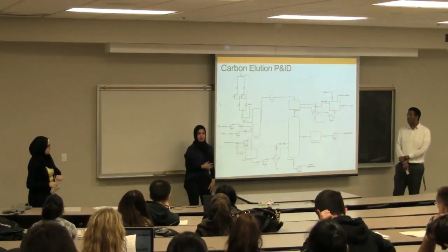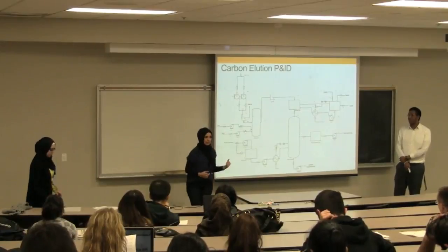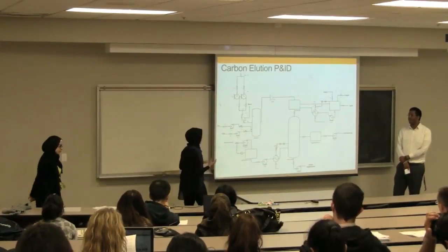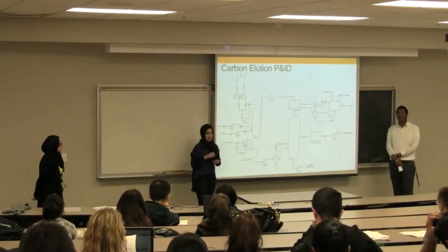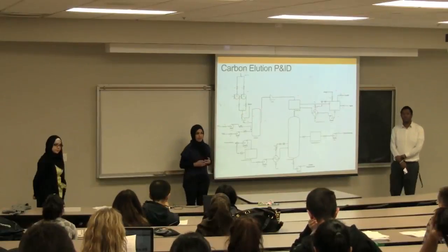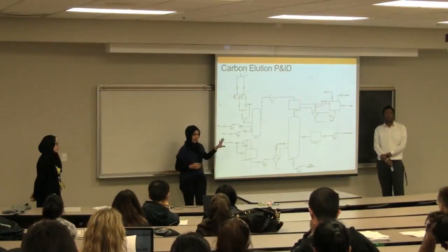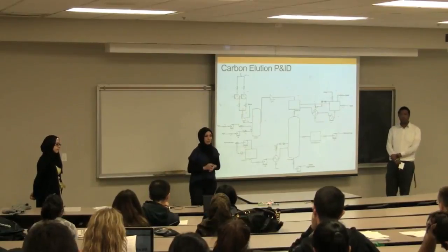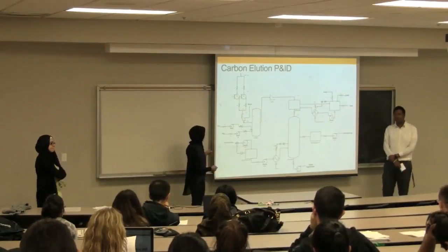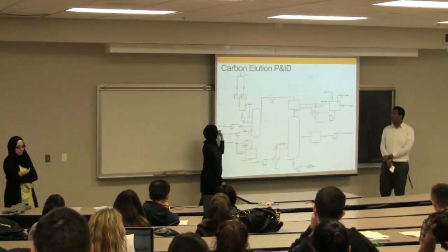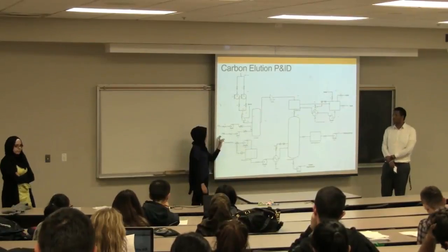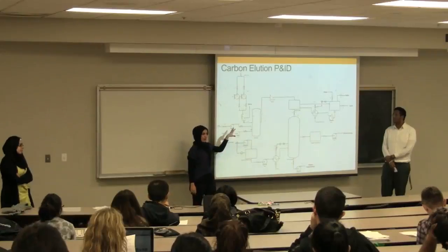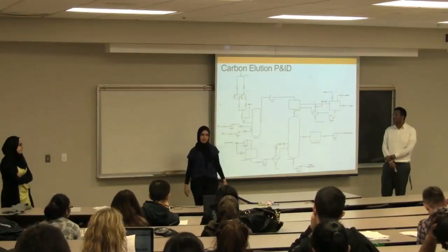which is actually a very important step because what we're doing here is we're trying to treat carbon fouling. Carbon fouling is essentially the buildup of soluble and insoluble materials on the carbon active site. It's important that we dissolve these foulants because we don't want the gold to be competing for these active sites with other materials. So in order to do that, we have to pump hydrochloric acid and water and essentially go through a washing cycle. It's typically 20 to 40 minutes long.